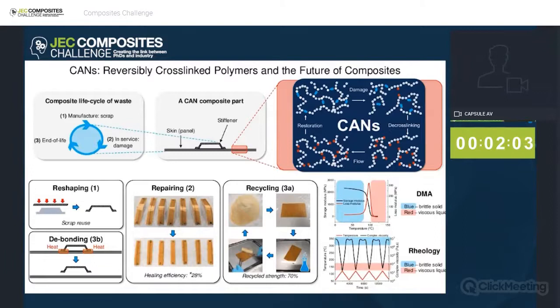Now in the rheology below it, we can see again the black curve sharply drops off as temperature rises, and this follows the decross-linking process. Then as the temperature is reduced, it recross-links again, and importantly, we can see that this process is repeatable again and again and again. Now, if we have a polymer like this, we put it into our composite as our matrix, there are several ways we can apply this to improve the composite life cycle and make it more sustainable